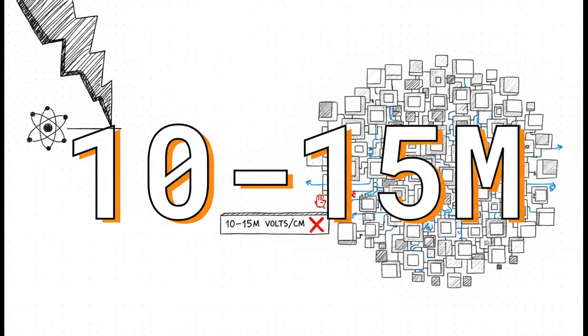But the absolute ultimate superpower of this dielectric is its jaw-dropping breakdown field. We're talking 10 to 15 million volts per centimeter. Just take a second to really conceptualize that. To break through this microscopic barrier, you would need the equivalent of a lightning bolt's electrical pressure scaled down to the atomic level. No way, right?